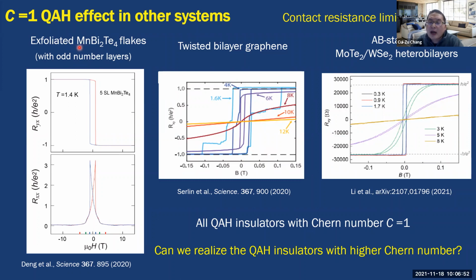The first system is the exfoliated 2D material, exfoliated manganese bismuth telluride, an intrinsic magnetic TI in the 1-2-4 phase. With odd numbers of layers, we could realize the quantum anomalous Hall effect. And in twisted bilayer graphene, this is not the magnetic doping approach, and here we could also realize the quantum anomalous Hall effect. And just more recently, in AB-stacked MoTe2 and tungsten selenide bilayer structures, the quantum anomalous Hall effect was also realized.